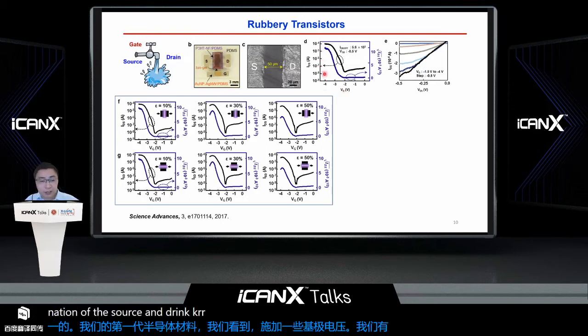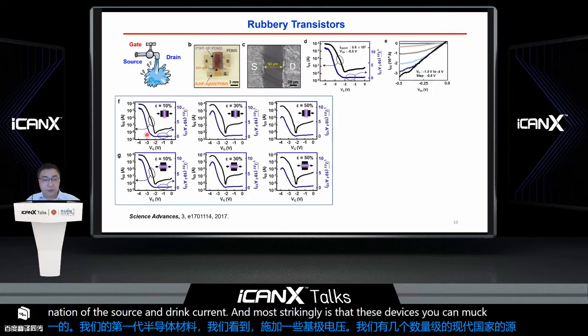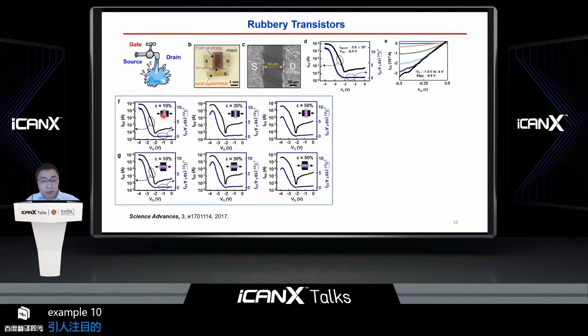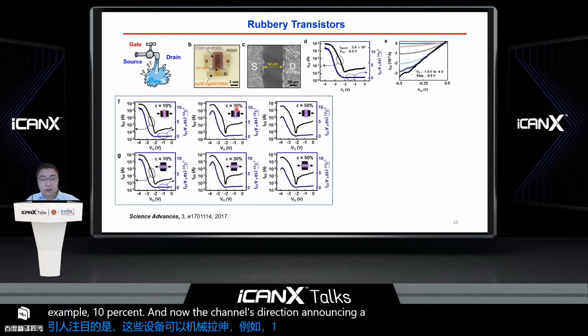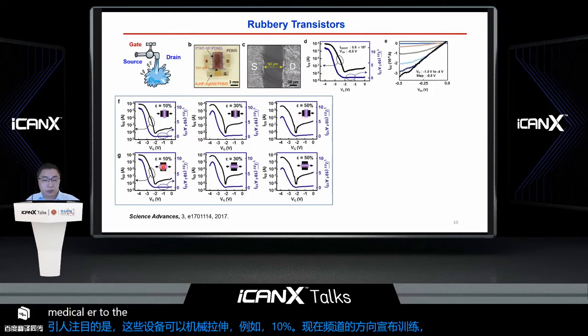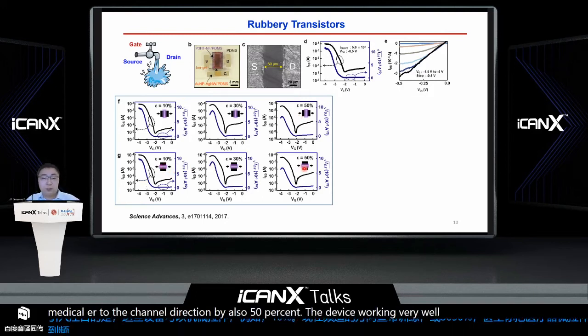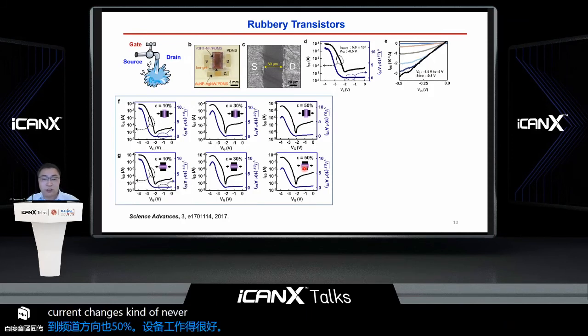And most strikingly, you can mechanically stretch these devices, for example, 10% along the channel length direction, along source and drain, or by 30, 50%. Even if you stretch perpendicular to the channel length direction by 50%, those devices work very well. But we do see some current changes; the source and drain current level have certain differences.